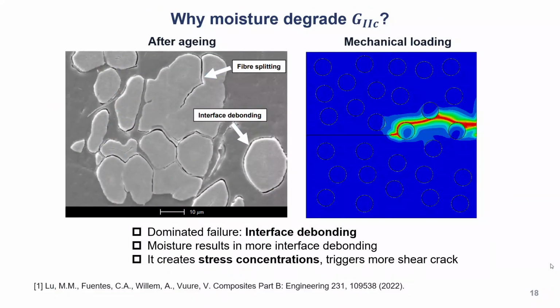So why does moisture degrade the mode 2 fracture toughness? As I said, the dominant failure mode is the interface debonding in such a case. Because moisture can result in more interface debonding, this can trigger greater stress concentration and trigger more shear cracks.